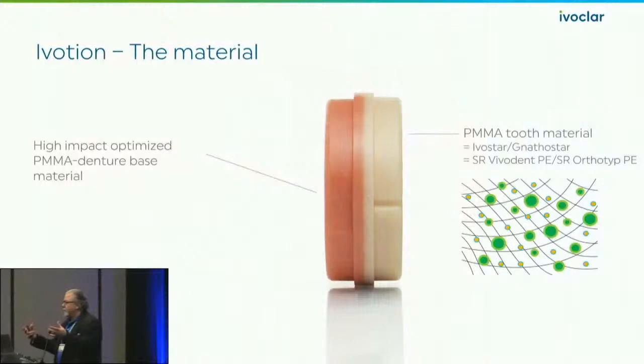But once you start going beyond that, you start to really cause damage. The longer PMMA stays at that high temperature, the chemical properties begin to change, and now you start losing that high impact property. So the fracture toughness starts to diminish, the material becomes brittle. And so we know that this big disc, polymerizing it and trying to get it all done in 35 minutes isn't going to happen. So the sacrifice is, there's 2 standards for high impact material that it has to meet to be called one. This slightly falls below one of those bars.